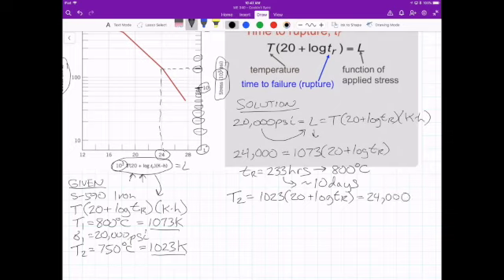And then we solve for TR again. So our second TR, call this TR1, this is TR2. Our second TR, just a 50 degree drop in temperature, I get a much larger time. 2,890 hours. This is at 750 degrees C. And this is approximately, let's see, 2,400 would be 100 days. So this is probably about 120 days, approximately. So just a 50 degree decrease, same stress being applied to the material, the material lasts 12 times longer.